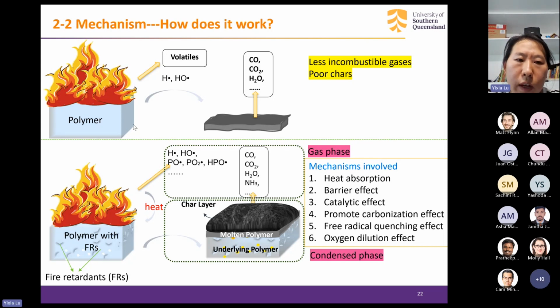For polymer without fire retardant, of course, there are volatiles, hydrogen-free radicals, and some gases, as well as water, generated in the combustion, but there are less incombustible gases, and the chars are poor, so the polymers usually burst out. But for polymers with fire retardants, there exists heat transfer, PO, PO2, and HPO free radicals quench the H and HO free radical reaction, and also we can see much more char layers are generated on the surface of the polymers.